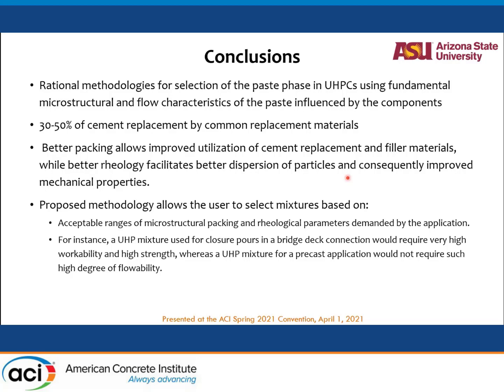Then go into the aggregate phase, again use a compressible packing model, come up with the packing of the aggregates, and make sure that you have enough paste to fill in the voids between the aggregates. That way we can design a very functioning, very compact, and very efficient mixture without having to waste a lot of other materials. So high workability and high strength would be required.